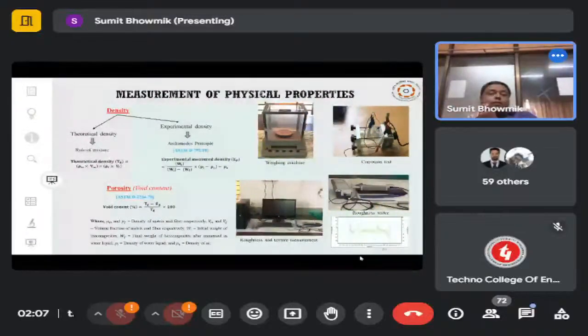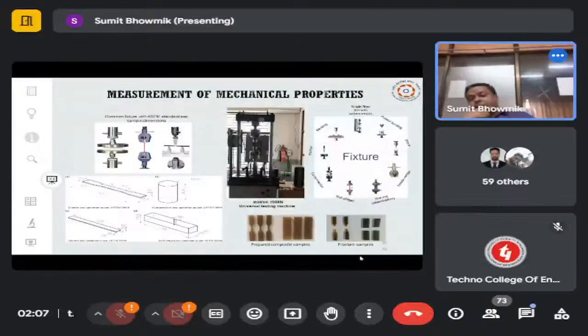One is the experimental density based on the Archimedes principle, where you have to absorb the water, find the density of the water and the weight difference of the component, so that you can find the volume and the density. In the same way, void content also needs to be determined, and every test has to be carried out according to the ASTM standard. Some ASTM standards have been mentioned here, which need to be followed in different conditions, so that density, void content and water absorption capacity can be determined.